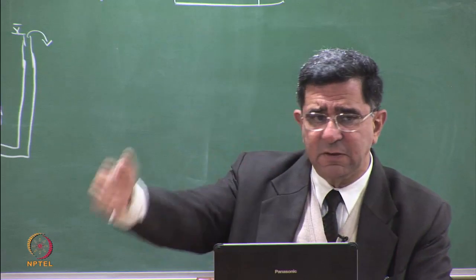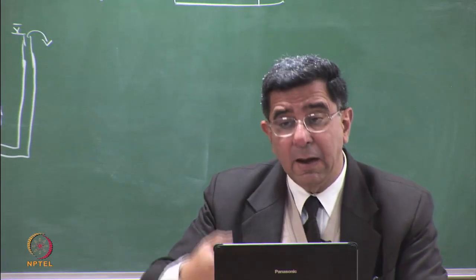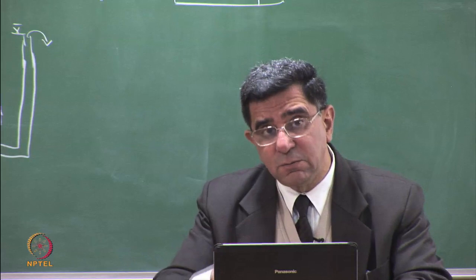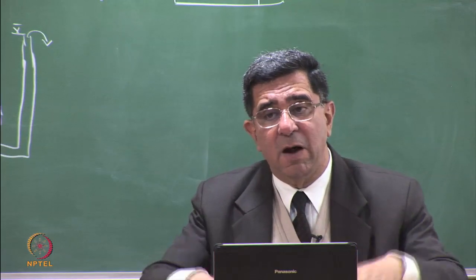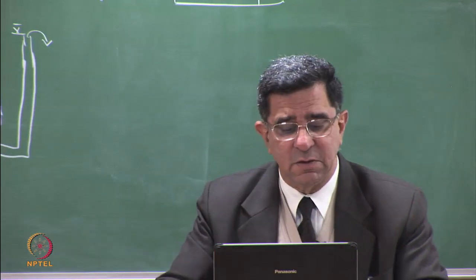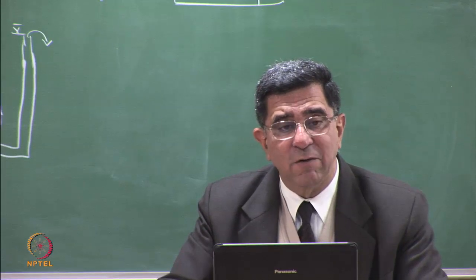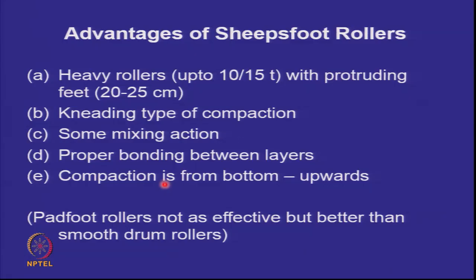You will have to use some disc harrows. You can try that. But here, while the sheep's foot roller is moving, it is making pock marks and the clods are breaking and the water is mixing properly. It allows you to have proper bonding between the layers and compaction is from bottom upwards. You can also use pad foot rollers, which have smaller protruding feet than sheep's foot rollers, but they are not as effective as the sheep's foot roller, but they are better than smooth steel drum rollers.